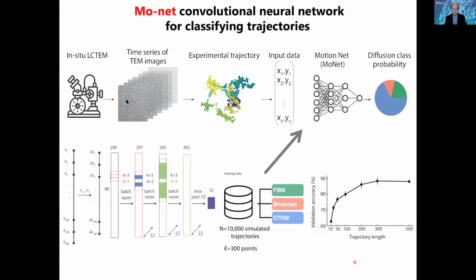So while we were in the COVID-19 break, my colleagues, Vida Jamali especially, working with her colleagues, developed a neural network. We call it MoNet, and the MoNet neural network takes hundreds and hundreds of these images. Every trajectory is then analyzed based on whether the most likely distribution of motions looks like fractional Brownian motion, or Brownian motion, or continuous time random walk. And so we're able to take vast amounts of this data and see which model it is most consistent with using this neural net method.